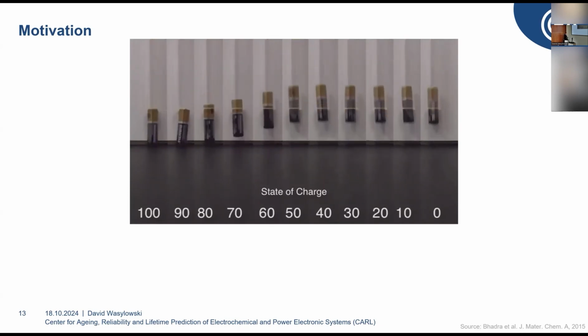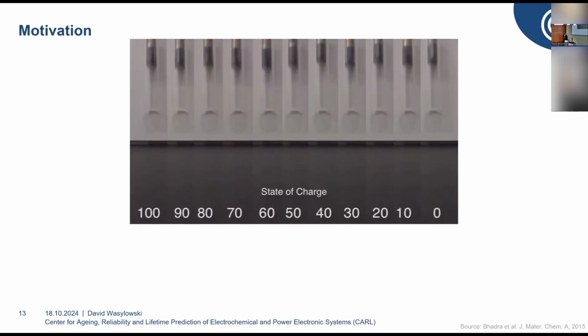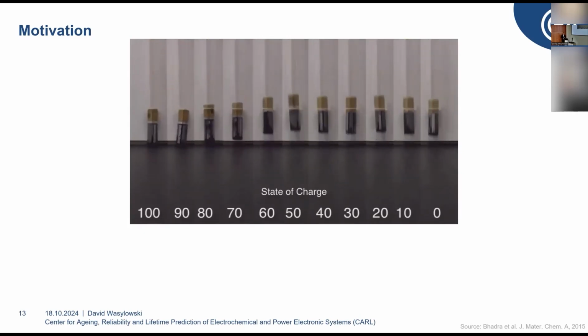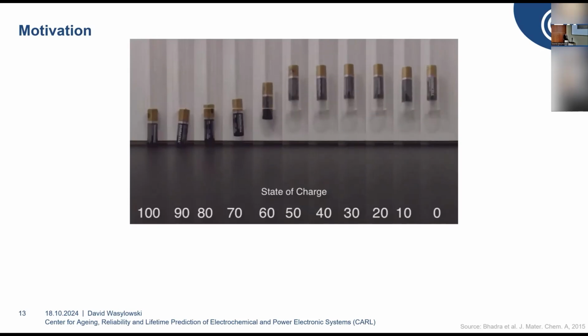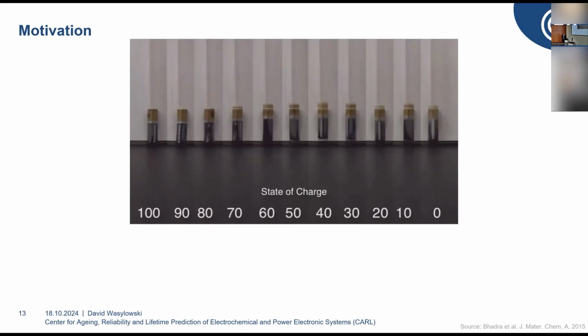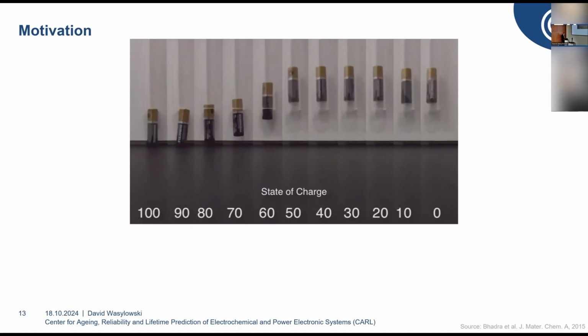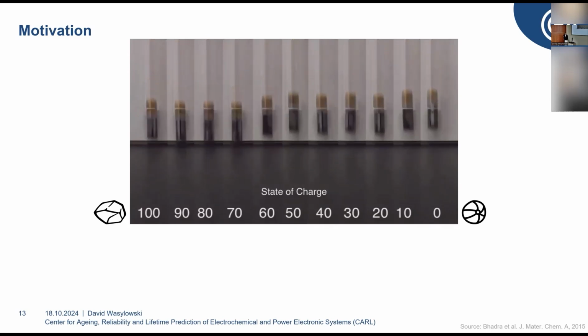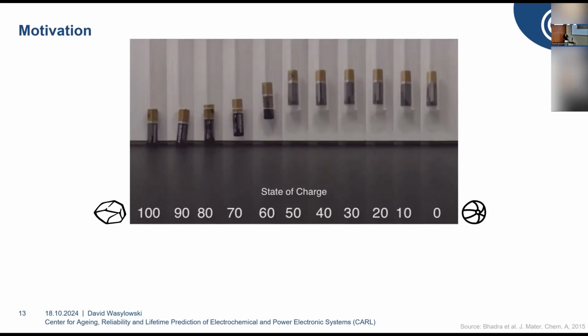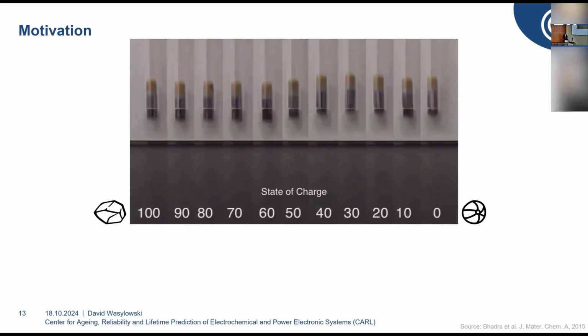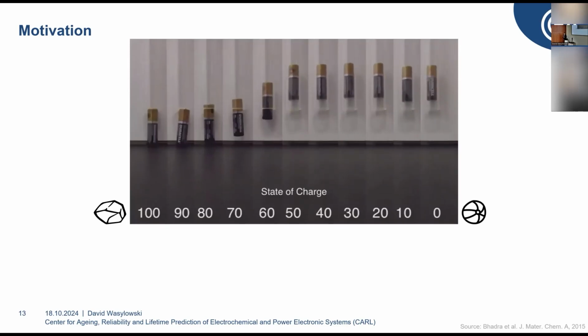And we know from electrochemical fundamentals that these types of batteries change their density distribution and their Young's modulus during cycling. So they go from this dry and hard paste when they are fully charged to this soft, lumpy mass when they are discharged that looks like gelatin. You might also say they behave like a rock when they are fully charged and like a rubber ball when they are discharged. And these types of drop tests are great for an initial demonstration, but they are difficult to reproduce when you have different cell designs. And we really need something that is more quantitative.